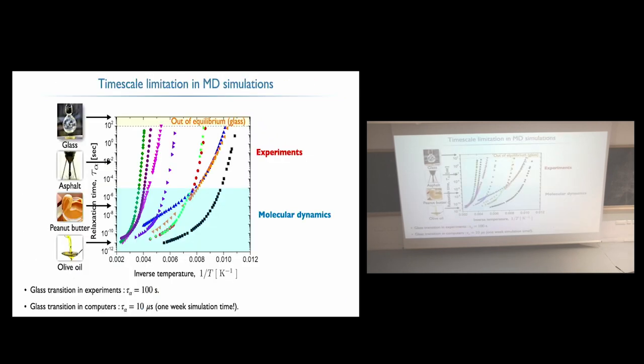If we move to the next slide, which makes it clearer, here you have the relaxation time. In experiments, this is setting what's a glass. So in experiments, when tau alpha is 100 seconds, this is a glass. But in simulations, if you do 1 week of simulation time, which is already quite long, this is our 100 seconds. Basically, you reach only tau alpha of around 10 microseconds. So it means that the computer glass transition happens here, at temperatures that are much, much higher than what you have in experiments.